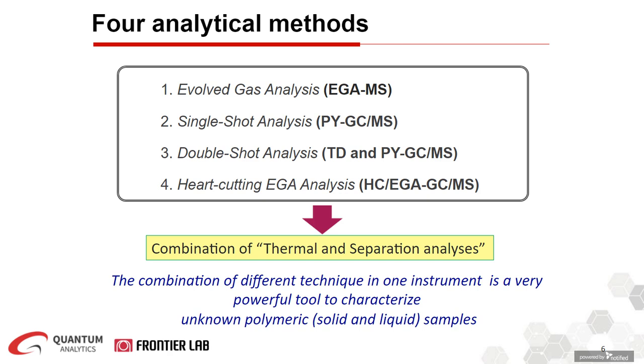The multi-functionality, purpose and capability of the microfurnace pyrolyzer allows you to perform 4 main analytical techniques. You can simplify pyrograms and chromatograms by combining these techniques in accordance with the purpose of your analysis. So your data analysis becomes easier, more targeted, rapid, and effective. You could perform evolved gas analysis, EGA, which is a thermal analysis of a sample. From the obtained EGA thermogram, you can understand the behavior of the sample toward the temperature by temperature program heating of the sample and directly detecting the evolved gases with MS.